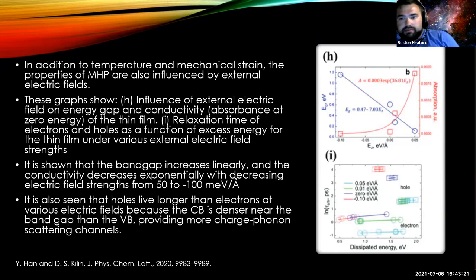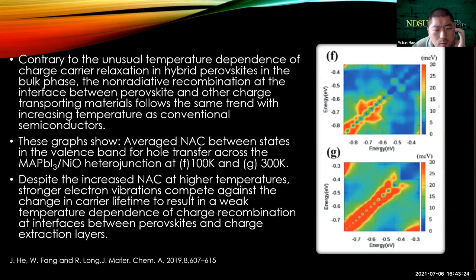So in addition to temperature and... Can you go back one slide? Yep. So what's the meaning of this graph? The graph on the right. So that's the non-adiabatic coupling between different states in the valence band for hole transfer across a perovskite and a nickel oxide junction at different temperatures. So it's showing that the coupling is stronger at higher temperatures than at lower temperatures.